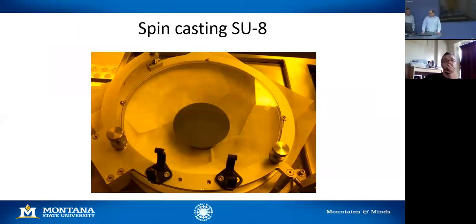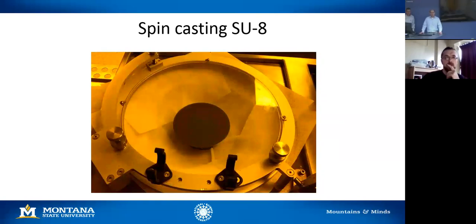So I talked about spin casting. One of the issues, and here's a short little video of SU8, which is a photoresist. We call it an epoxy. It's a photosensitive epoxy, a negative resist. One of the problems with this is this resist spins at probably about 1,000 RPM. You see the color sweeping over the wafer. It's a transparent material, visible light, and the color has to do with the thickness of that film. If you look carefully, you still see a color variation across that surface. When you're spinning films this thick, it's very difficult to get good uniformity.